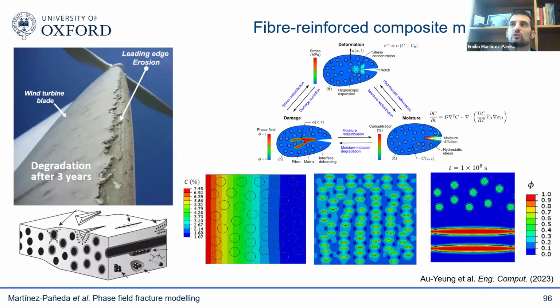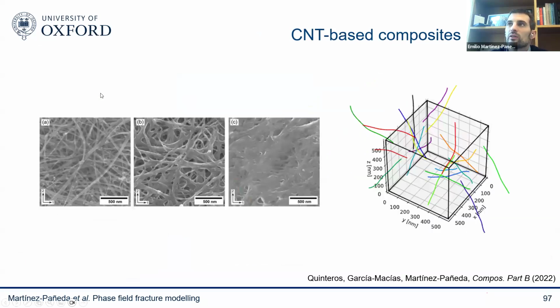And lately, we have also extended this to deal with multi-physics environments. So this is work in collaboration with Wei Tan at Queen Mary, University of London. And it's particularly of interest to wind energy. There are a lot of cases where we see a lot of degradation due to the environment. Again, we're interested in interdisciplinary civil engineering problems. So there's a big effect of the environment. But what we can see is that we can simulate those coupled problems, similar to the battery problem. You can simulate the transport of humidity, and you can simulate the interplay with mechanics and with fracture, and we can capture the behavior of those components.